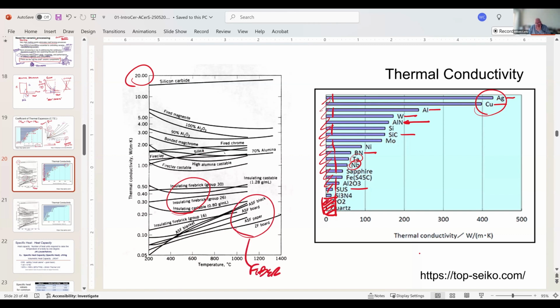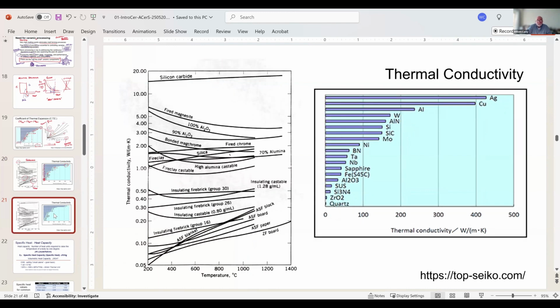fiber refractories. So you see that all of these materials shown on this plot, this is refractories here, have thermal conductivities that are in the noise of this data. Okay, so everything else is going to be much higher thermal conductivity. These materials were actually designed to give us low thermal conductivity because we want to use them as insulators in furnaces, and they also benefit by having very high melting points. Okay, this is a duplicate slide, so I remove it.